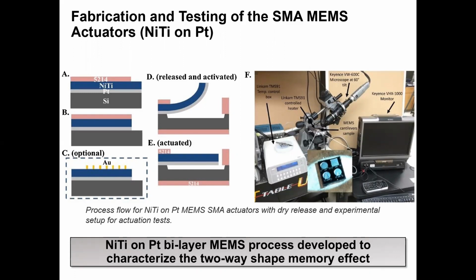A rate-controlled heater programmed a small heating stage where the MEMS chip was fastened, and a high-resolution microscope, which was capable of tilting, was used to capture images and video of the thermal actuations. I found that by depositing a thin film of platinum underneath the NiTi, a bimorph structure that exhibited a curled state when released from the substrate can be thermally cycled to achieve the two-way shape memory effect. Then by studying different combinations of NiTi and platinum thicknesses and comparing these results to an analytical model, I revealed that curvature was influenced by these parameters. So upon heating, the NiTi platinum bimorph would actuate towards the substrate, the position in which they were shape set or annealed.